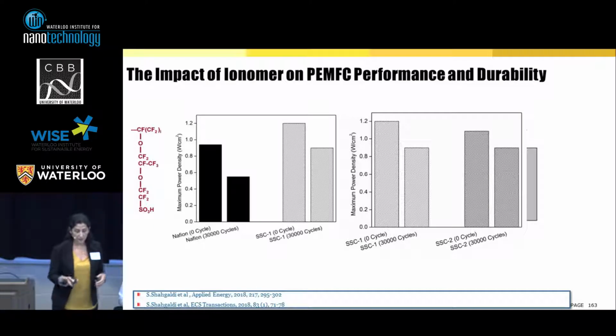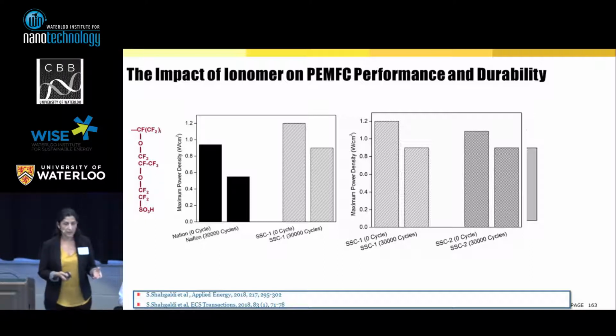For example, here we compared the Nafion with the equivalent weight of 1,100 with another of almost the same structure, named short side chain, with the lower equivalent weight of 800. So we find that with a little bit of change, the difference is going to be huge in terms of performance and durability.